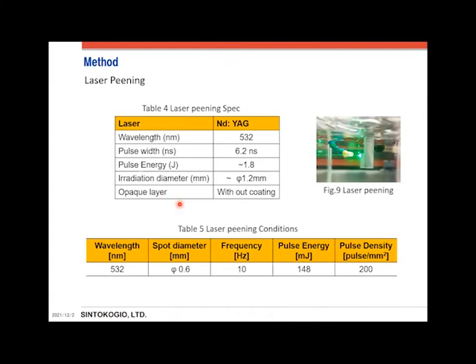Next, I will explain the simple specifications of the laser transmitter used in this project. The laser type is Nd:YAG laser. The laser is visible light of 532 nanometers, the second harmonic. The pulse width is 6.2 nanoseconds, which is a nanosecond short pulse. The opaque layer is not put on, but the laser peening is done in water as shown in this picture. In this experiment, the spot diameter is set to be 0.6 millimeters, and the pulse energy was set to be 148 millijoules, resulting in a pulse density of 200 pulses per square millimeter.